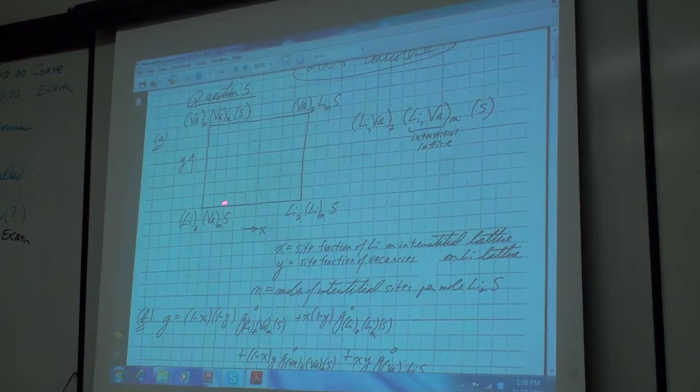Over here, we're going along this way, putting lithium ions into the vacant interstitial sites. So this is your hypothetical compound where all the interstitial sites are occupied by lithium. I've written an N here because it isn't given in the problem: the ratio of lithium sites to interstitial sites. If you have Li2S, how many interstitial sites do you have? Are they the face centers, the tetrahedral holes, the octahedral holes? We're not sure of the ratio, so I just put an N. This is the number of interstitial sites for every two lattice sites. It's unknown in this particular example.